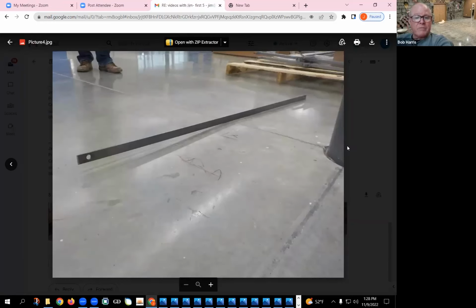If it's poured on top of a vapor barrier, at construction joints, the way that the reinforcing steel passes through the construction joints can affect curl, and site conditions like ambient temperature and humidity, all of these things can affect curl. But getting back to the polisher's perspective, you know what's going to happen if they just run their power trowel or their walk-behind planetary grinder over that. You're going to have exposed aggregate right at the joints. And what if the client's not wanting that?